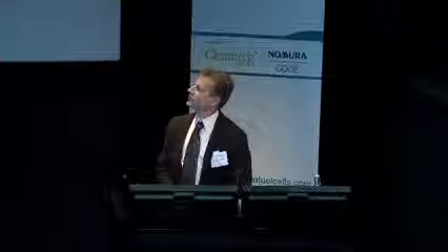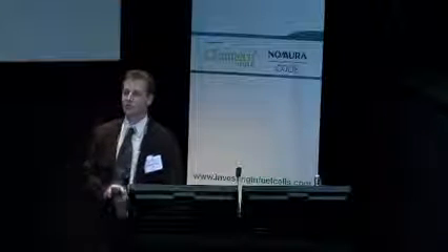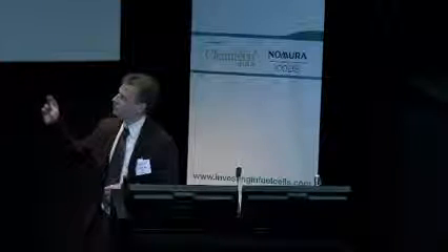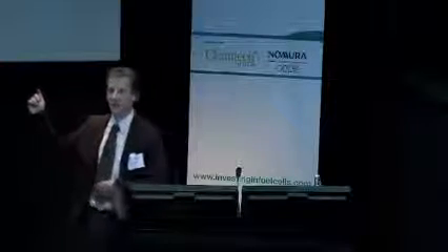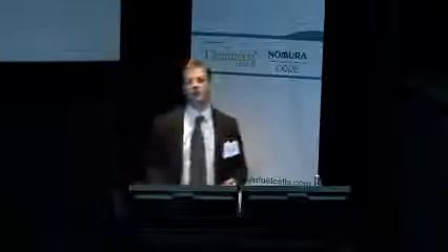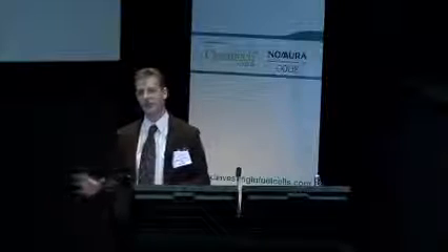Another standard which has been stated is that the DOE suggests that all novel, non-platinum materials should have an open circuit potential of above 0.9. So we also achieved that. We've also done, as I said, some stability cycling tests. This is an interesting one I put in because if you look, the initial behaviour of this particular MEA was actually not as good as the one I showed you previously. It's a different loading, and there's some sort of mass transport issues. What we've shown here is that through the course of the 30,000 cycles, the performance has increased back towards the levels shown in the previous slide. So essentially what we have demonstrated on several different MEAs is that the materials are stable in this potential region over 30,000 cycles.